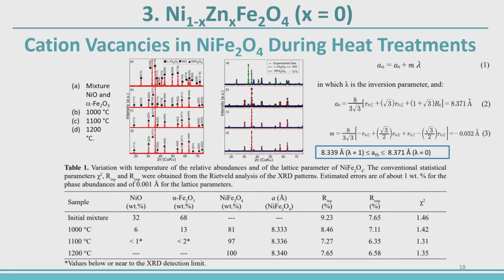We want to show that, using 3 or 4 techniques, we propose that perhaps with thermal treatments at low temperatures (not low, but compared with the others), cation vacancies at the octahedral sites can be formed, and these are gradually filled with iron as the temperature increases. That's what we want to show experimentally is happening in our samples. So what we did, we mixed nickel oxide and hematite by ball milling at very low energy, just to mix the powders, and then we submitted it to 3 different temperatures.